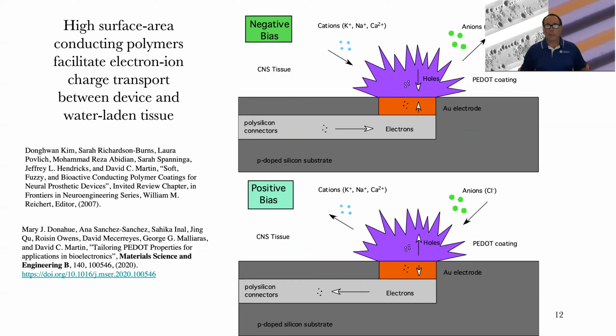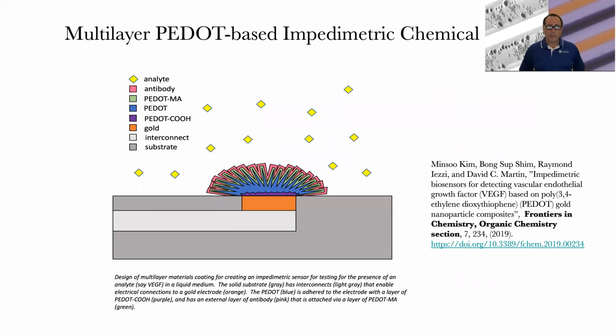So there's just lots of room for charge exchange, particularly when you're going to put a device into an ionic solution like a tissue. And so you're pulling cations in and out, you're exchanging that with hole transport in the polymer. You exchange holes with electrons at the polymer metal interface, and typically these devices are operated at 0 net voltage so that you're not doing any electrochemistry. So that very dramatic drop in impedance is extremely important for biomedical devices of various sorts. It opens up the opportunity for building lots of interesting specialized devices that would do particular things.